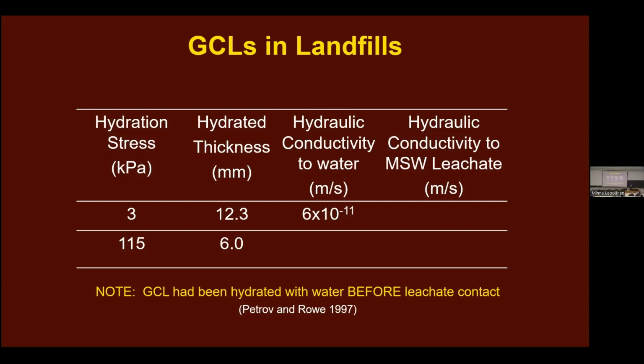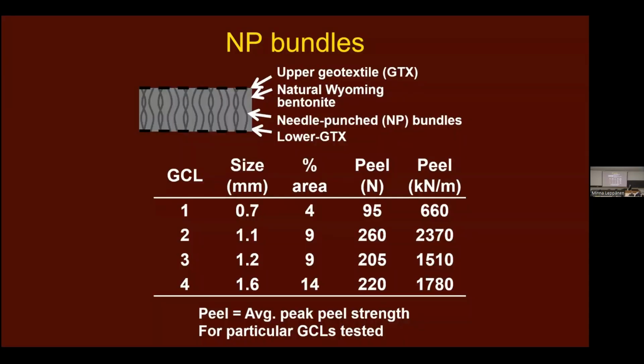The hydraulic conductivity to water under 3 is still not bad, 6 times 10 to the minus 11, just off the spec sheet, which is at 35 kilopascals. But when I permeate it with leachate, it goes up an order of magnitude to about 6 times 10 to the minus 10. You'll see peel strength is indicated there. The minimal bundles gave what is normally expected to be a reasonable, adequate peel strength of 660. As you increase the needling, you see the peel strength goes up. Most people would say that's great.